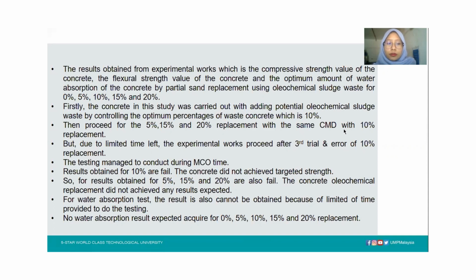But due to the limited time left, the experimental work proceeded after the third trial and error of 10% replacement. The testing was managed during MCO time. The result obtained for 10% failed. The concrete did not achieve the targeted strength. The results obtained for 5%, 15%, and 20% also failed. The concrete with oleochemical replacement did not achieve any expected result.